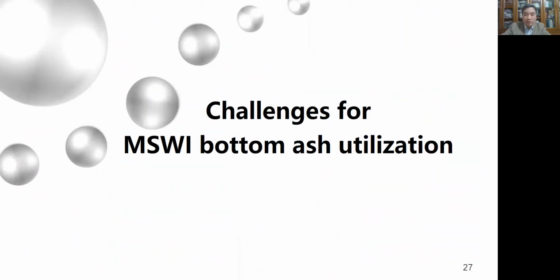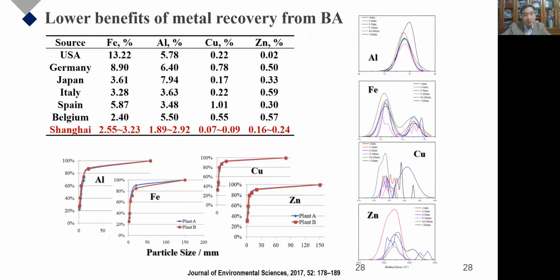Now, let's talk about some challenges we confronted during bottom ash valorization. The first challenge, according to our study, is that the bottom ash in China contains relatively low metal content, and this also influences the quality of the bottom ash material. The ferrous and non-ferrous metals need to be refined before utilization, as they are partially oxidized during incineration.